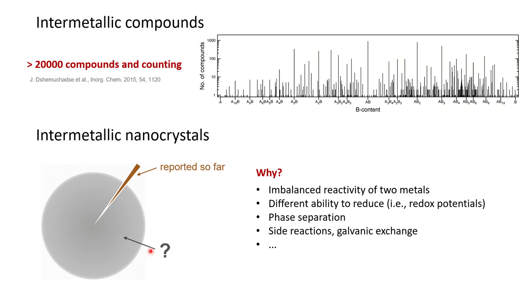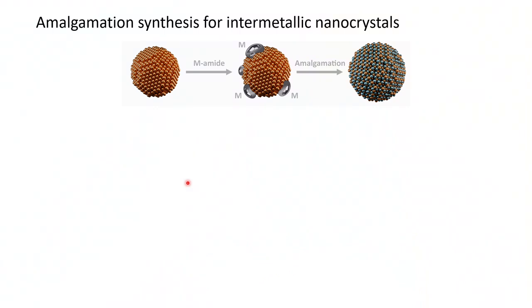So we asked ourselves at the beginning of that project why this is the case, and the basic answer is just that metals are very dissimilar. Different metals have different abilities to reduce, and in the flask, as soon as one metal goes to the metallic state, it pushes away the second one. These are so-called redox reactions, for example galvanic exchange, and different side reactions, which prevent us from making homogeneous intermetallic nanocrystals. So we set ourselves a goal to make intermetallic nanocrystals even when combining very dissimilar metals, like gold, very easy to reduce, and gallium, very difficult to reduce. And this is how we went about it.